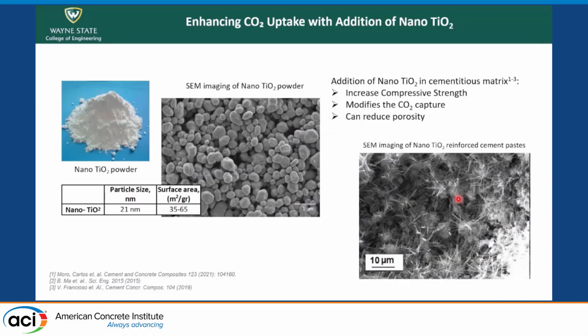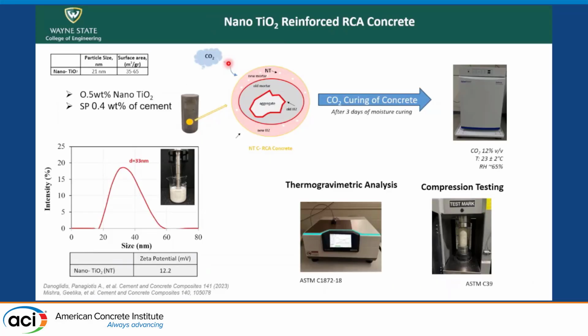As Marian discussed, titanium oxide has been widely mentioned in recent literature as able to modify CO2 capture. So we chose it as our initial nanomaterial that we're going to introduce into our new mortar to study the effect of nano-titanium oxide. We dispersed this nano-titanium oxide at an amount of 0.5% in water and added this to the cementitious matrix.